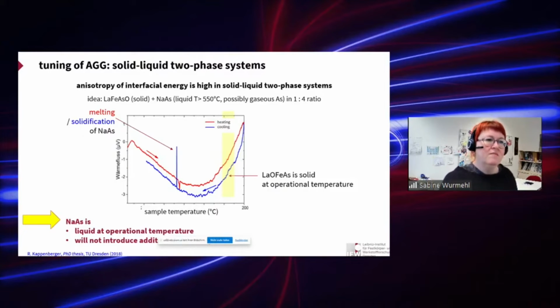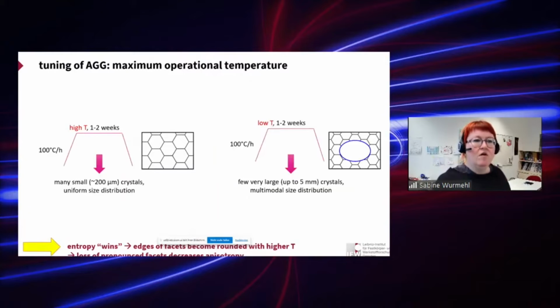Sodium arsenide as the inducer for the anisotropy is also beneficial because you have at least the arsenic as another component in your target phase. So, of course, you need to decide on the maximum operational temperature, and one ingredient is that the sodium arsenide is liquid, but the target material is not.